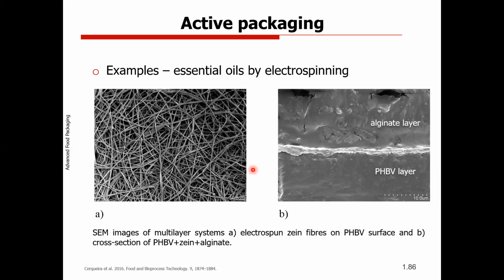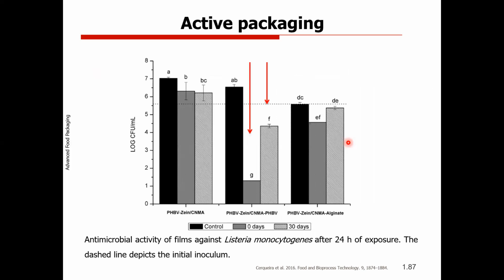So we tested different structures. We produced a PHBV layer with only zein fibers. We tested PHBV with zein and another PHBV layer, and we tested PHBV, zein, and an alginate layer. This cross section that you see here is one of the examples. So you have a PHBV layer and then alginate. Alginate is from algae, so it's sodium alginate, and then we produce the films. We electrospun the fibers onto the PHBV, and then by compression molding, we make a very thin film. And we were able to reduce the microbial growth in two of the systems, but it was clearer when you use this kind of structure, PHBV, zein, PHBV.